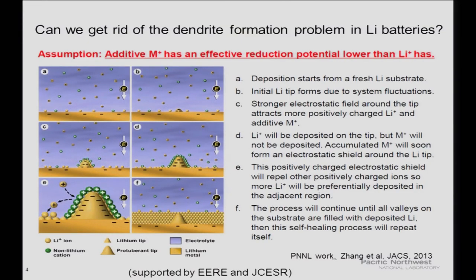I'm going to give you two examples. One is the anode material, which is where you form the dendrite. Thermodynamically, you always get this SEI formation, this dendrite. Is there any way you can change that situation so that if you form a dendrite, it will disappear by itself? This is a study currently supported by JCESR, where we are looking into chemical additives in the solution to make the dendrite self-disappear, what we call a self-repairing surface. I think this kind of new concept could lead to much safer batteries.